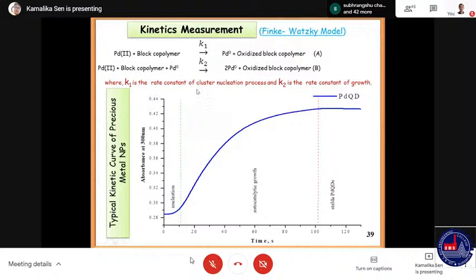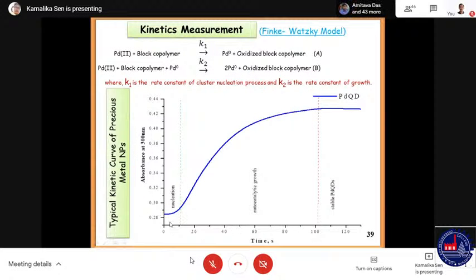Now this is the way how the kinetic measurement is done. This is the Finke-Watzky model. Here we can see our method. First, it's a very fast process. We have seen that only 3 to 4 minutes is sufficient. So if we see a time scan for about only 100 seconds, we can see only after 10 seconds the nucleation process has stopped. That means the stable region is finished after 10 seconds.